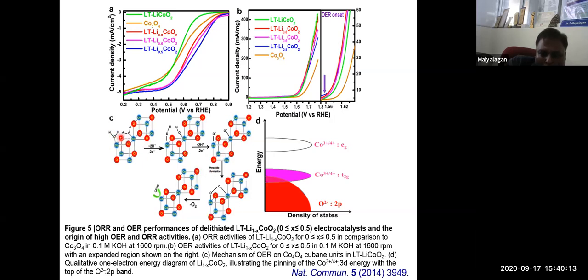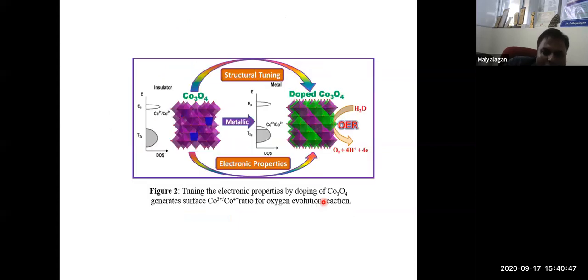Water comes and adsorbs on the cobalt site and forms OH, then it forms a radical, then a peroxide forms, and then oxygen is evolved. Similarly, nature does this beautifully in photosynthesis, where manganese clusters are used. So we took a low temperature lithium cobalt oxide, delithiated it, and overlapped the Co3+/4+ with the oxygen band, and it gives a better material.